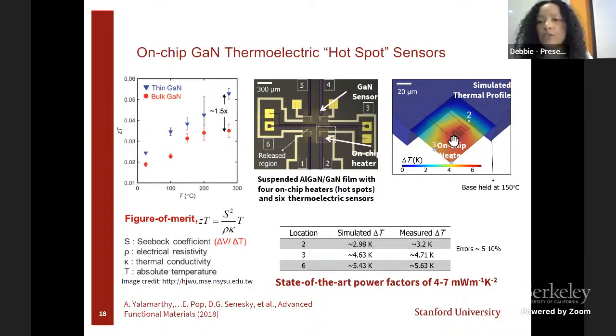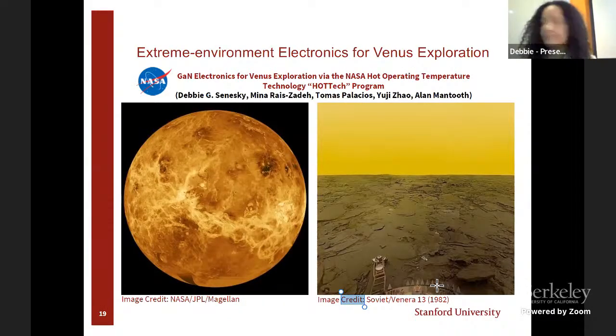So we can measure the temperature gradient and also validate it with our finite element modeling. And this translated to power factors between 4 and 7 milliwatts per meter Kelvin squared. We're happy with this number. So the idea is, could we scale these thermoelectric devices up, stack them up, and actually harvest heat gradients?